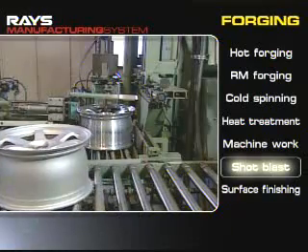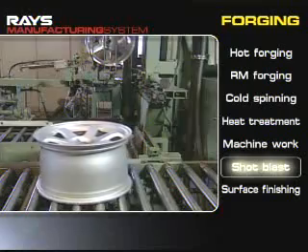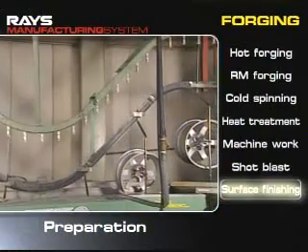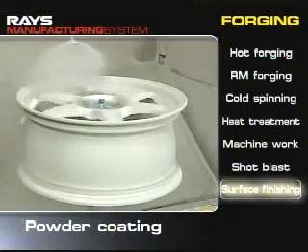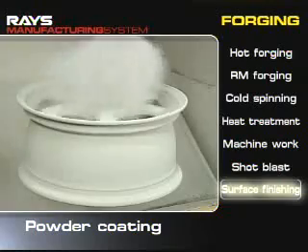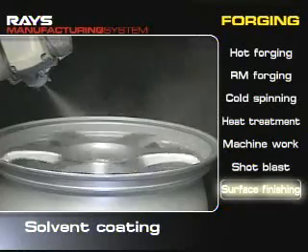After processing, the surface strength of edges is increased and shot blasting is performed to smooth surfaces. During finishing surface treatments, chromate films are first applied on the surface to protect the aluminum from corrosion. Fine coating materials with a diameter of one hundred microns are powder coated to improve smoothness. Then the wheels are spray coated — colored in line with their designs or clear coated to protect their surfaces.